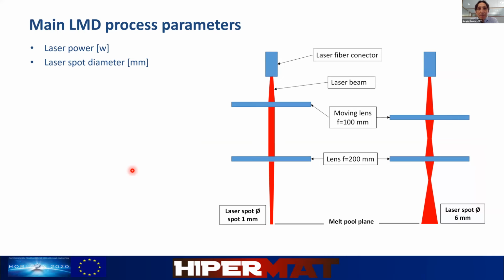There are many parameters that influence the LMD process, and we are going to see the main parameters. So the laser power is one of the key parameters. The more power, the more material is melted. The laser spot diameter is the size of the laser beam at the melt pool. Here, there's the melt pool plane.